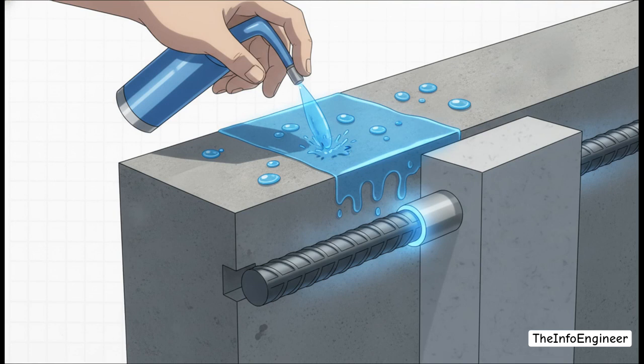But fixing the structural strength isn't enough if you don't stop the underlying chemistry. If you just patch a hole in a chloride-contaminated slab, the difference in electrical potential between your brand new patch and the old, salty concrete around it actually accelerates corrosion in the adjacent area. We call this the incipient anode effect or the halo effect. To prevent this, engineers deploy an advanced toolkit: zinc-rich epoxy primers, and sacrificial galvanic anodes that generate a small current to protect the steel. Then we finish the whole thing off with anti-carbonation breathable coatings and silane-based water repellents to lock moisture out for good.